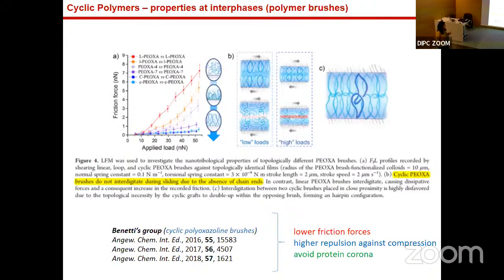This is very interesting: the polymer brushes with cyclic polymer brushes. This study, and many studies, have been done in the Benetti's group in Switzerland, where they have created surfaces, they have modified surfaces with cyclic polymers. By AFM, they studied how these two surfaces modified with cyclic brushes behave under friction forces. And they found lower friction forces in the cyclic polymer functionalized surfaces. They explained that it's because these cyclic brushes cannot interdigitate, they cannot interpenetrate, and that's why their friction forces are lower.